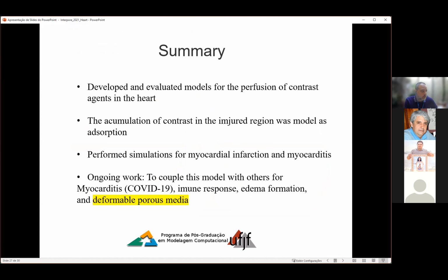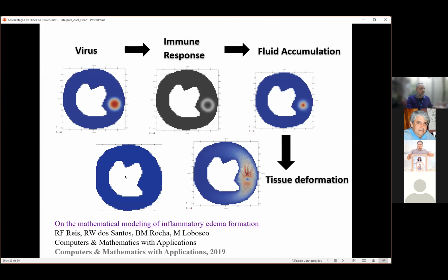So summary, we developed and evaluated models for the perfusion of contrast agents in the heart. The accumulation of contrast in the injured region was modeled as adsorption, as a classical model for porous media. We performed simulation of myocardial infarction and myocarditis, these 2 kinds of disease. And we have a lot of ongoing work coupling these models with other interesting models like the immune response, edema formation also, which is when we see the deformation of the porous media, the deformation of the tissue in the brain or in the heart, because you have accumulation of water during the edema formation. And we use the formalism of porous media for these kind of studies.